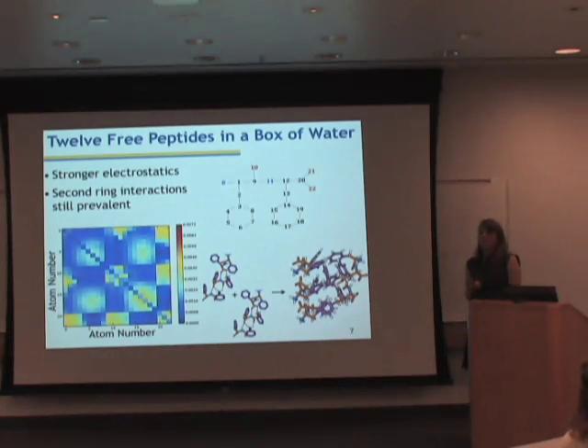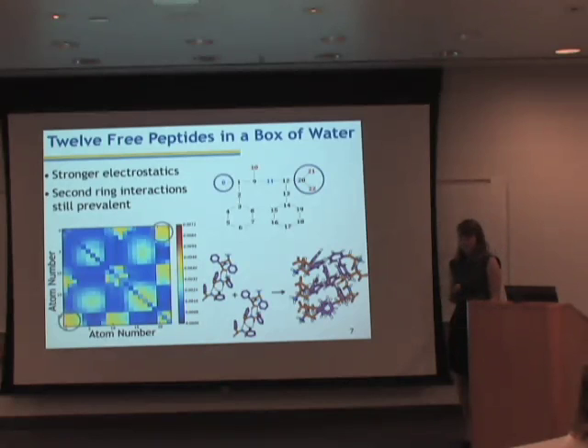The next thing we wanted to do was allow these peptides to float freely in water and see what happened and see if they formed any aggregates that resembled the crystal structure. We did this by simulating 12 free-floating peptides in a box of water. What we found is that the strongest area of interaction on this contact map is between the charged ends of the peptide, which contrasts from the crystal structure a little bit.